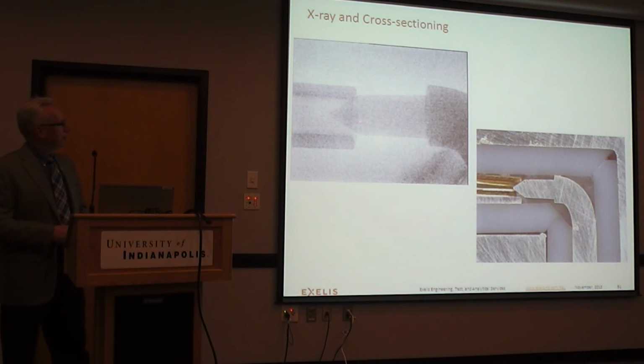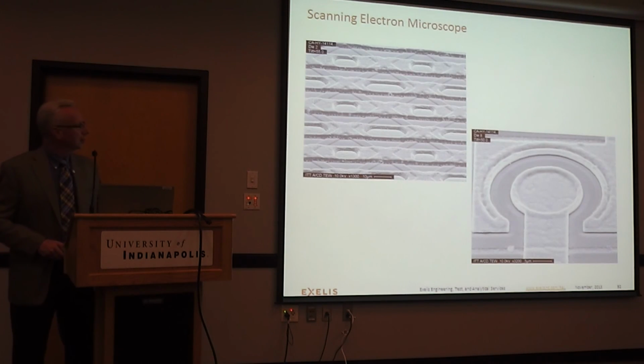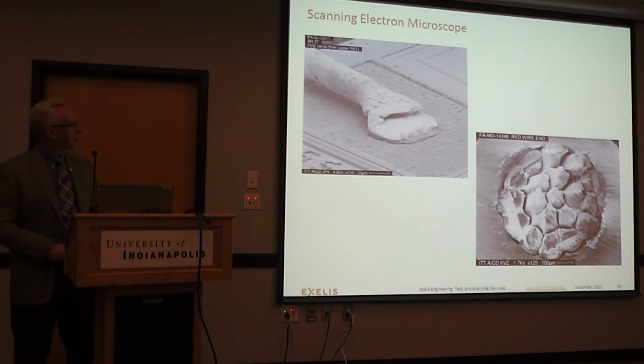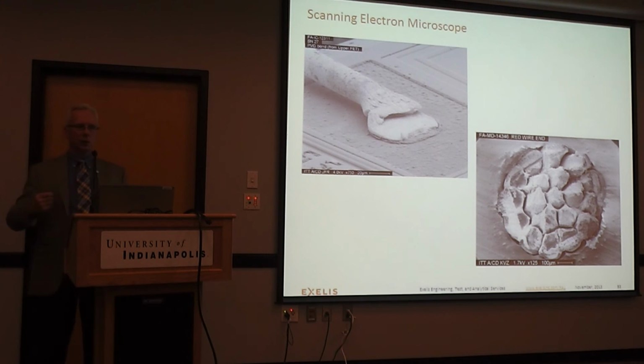Okay, that's an X-ray of an RF connector connection. You can see it's not completely engaged, male and female. Here's a cross-section of the same item, and you can see we have very good fidelity, both in cross-section and X-ray. It's a close-up of metallization on an integrated circuit, and there is a failed bond wire, or a bond wire getting ready to fail. It's about 75% fractured, and that's a stranded wire bundle down the bottom right hand, a stranded wire bundle that just failed due to tensile overload.